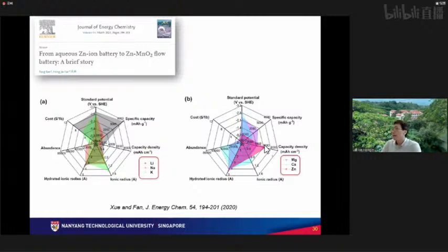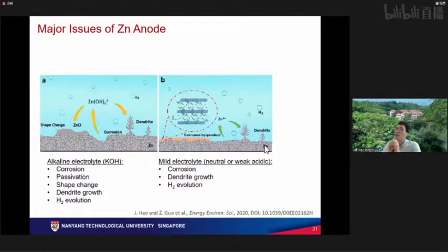So you need to overcome that. The capacity density and specific capacity are not the highest, but the volume density is okay. The specific capacity is 800 something, which is okay, but not comparable to lithium metal and potassium metal. But the capacity and density are not the big worries. The big worry is the stability. People know that with alkaline electrolytes we have many issues. We have corrosion because of the pH value, dendrites because of inhomogeneous deposition of zinc from the electrolytes, and hydrogen evolution reactions that generate bubbles.